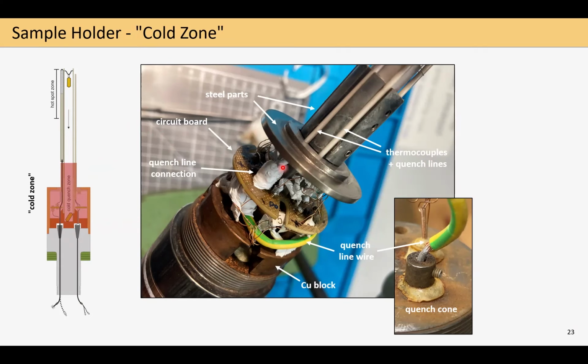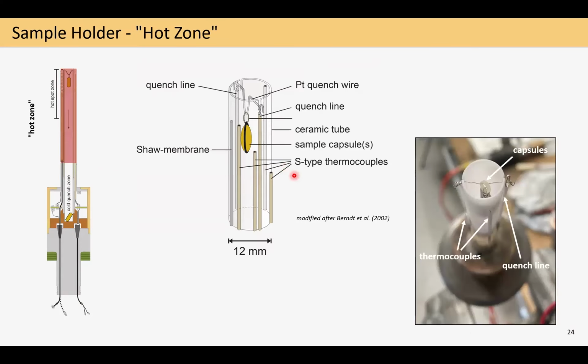Which brings me then already to the hot zone, where our samples are located and where we are measuring the experimental run conditions, for which we have a Shaw membrane for the fO2 and normally four thermocouples to monitor and control temperature. And the capsule is then suspended in a platinum wire here in the hot zone of the furnace. By the way, also here how this looks in reality.